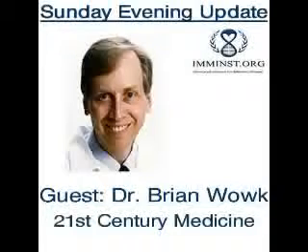So what we would really like, the ideal cryoprotectant, would be something that would look just like water. Something that mimics water, or a biomolecule, but that wouldn't freeze. So in a sense, that's what we try to do when we choose cryoprotectants in vitrification solutions: choose chemicals that look as most like water as possible, but that prevent water from freezing.